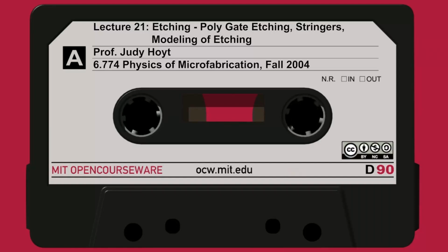That's going to do most of the work in getting you through the polycrystalline silicon. So you're just stabilizing at this point. You notice there's no power on the top and bottom electrodes, so the plasma's not on. You're not lighting a plasma. You're just stabilizing the flows through the chamber, and that takes a while. In this particular case, the stabilization step is about 20 seconds.